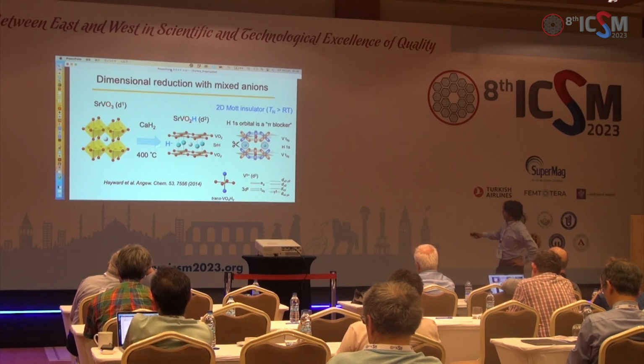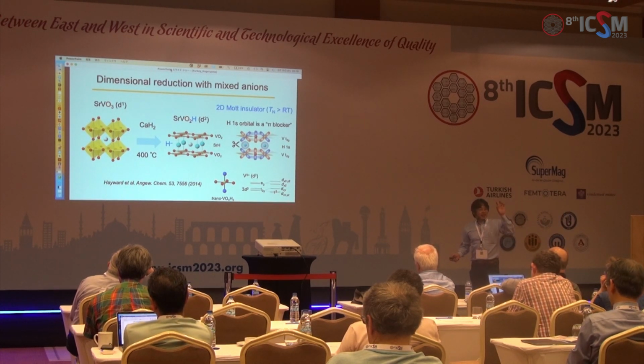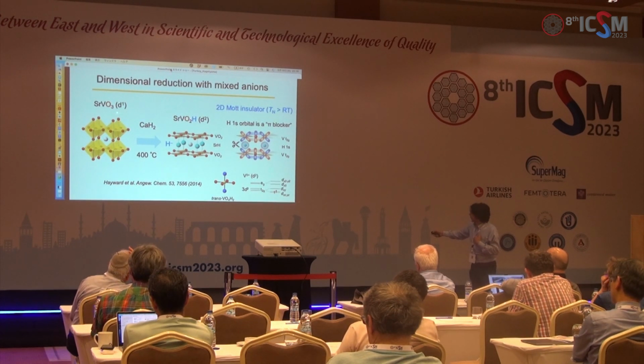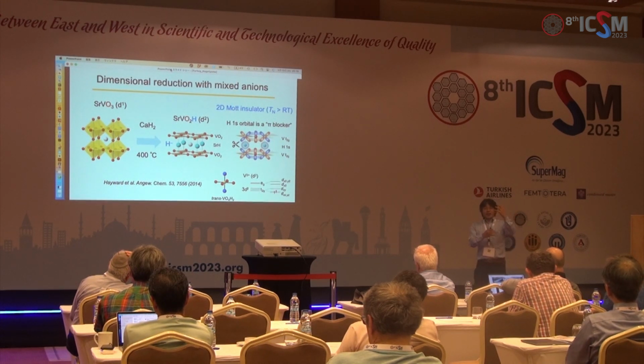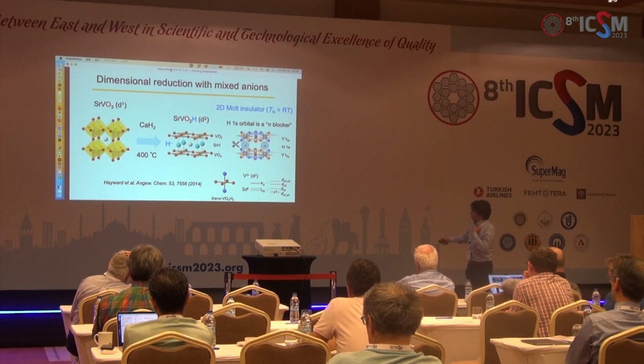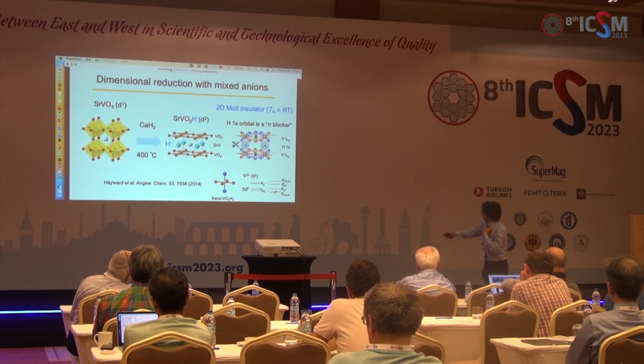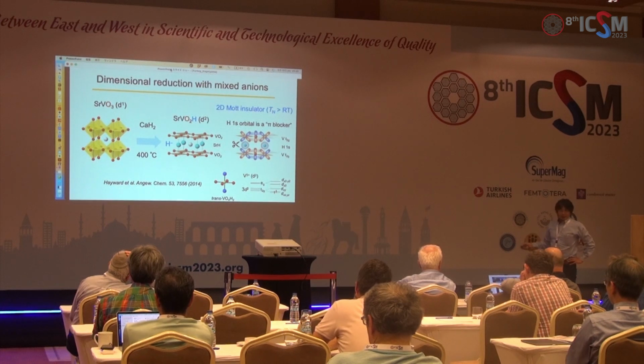So of course another important thing is the anion order. Actually 1/3 of the oxygen is replaced with hydrogen, but all the hydrogen are occupying the axial sites. So you have this type of trans coordination, vanadium O4H2. So this is the coordination, and that is arranging this. So anion ordering is occurring in this material.